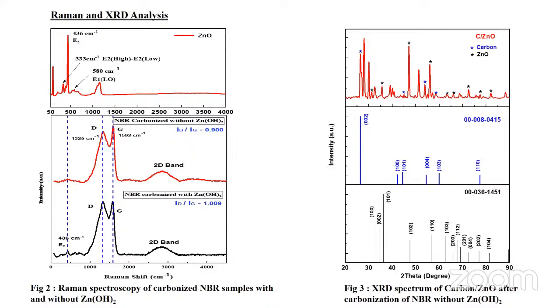The ID and IG value has increased with the addition of zinc hydroxide in the sample, which is due to the formation of more defects in the composite sample. In the XRD spectrum, we can clearly see characteristic peaks related to the graphitic carbon and the hexagonal wurtzite structure of zinc oxide in the carbonized composite sample.